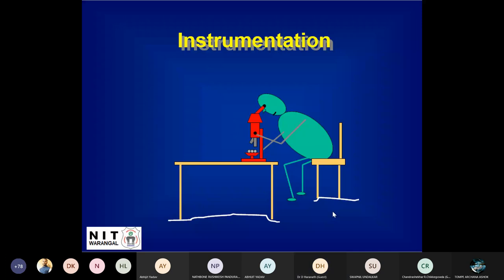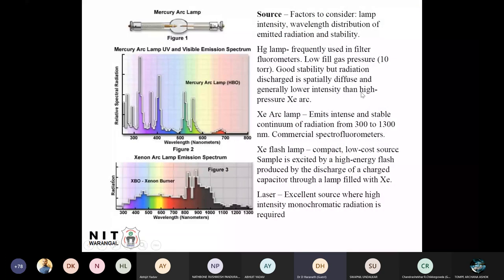Once you are able to successfully make such materials, how can you use instrumentation techniques? Usually when you want to record the spectrum of such a luminescent material, two types of lamps are available. One is the mercury vapor lamp, another is the xenon vapor lamp. Mostly the xenon vapor lamp is used in spectrometers, because the mercury vapor lamp, which was used earlier, is also a discharge lamp, but some of the wavelengths are missing. It starts from 200 to 700 nanometers and a little bit of IR, but some peaks are very strong and suddenly it drops down to zero.